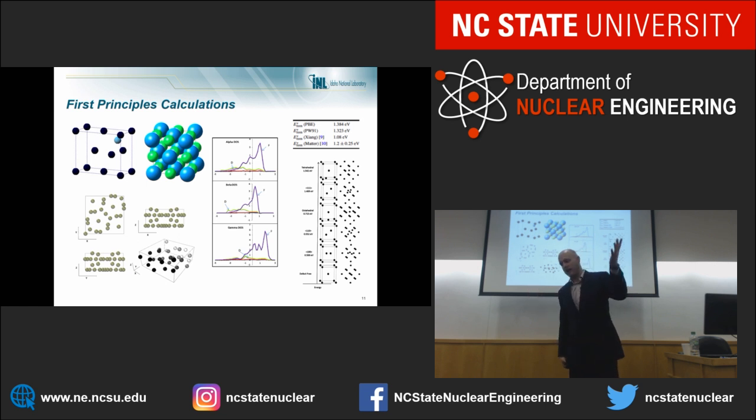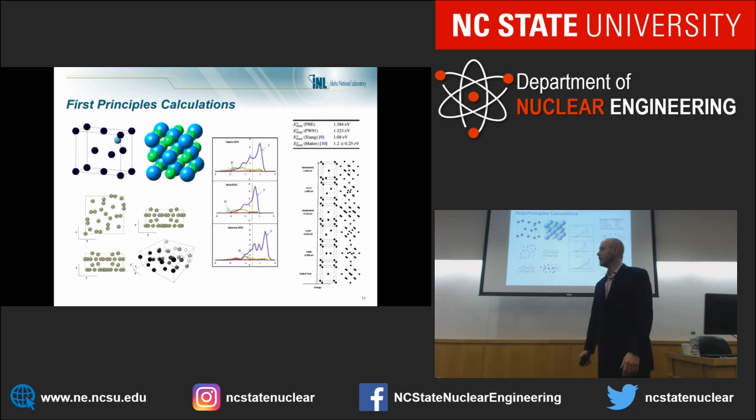But we've gone back now in fairly recent work that was just submitted and done ab initio MD. So we aren't making any of the approximations on restricting the number of atoms to move. We're allowing it to free flow and do whatever it does, and the results match up incredibly well. So it's hard to believe, but it's extremely easy to form point defects in these systems, and it behaves almost unlike any other metal that we know of.